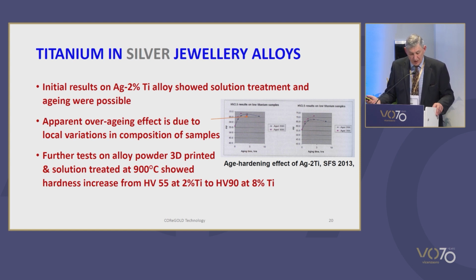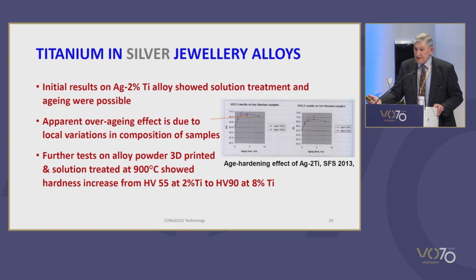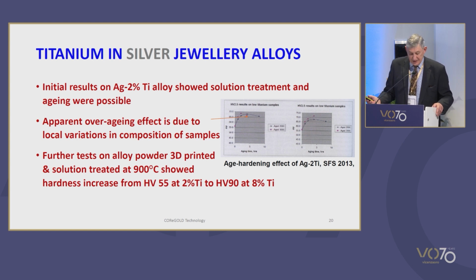The figure gives some results on samples solutionized for 2 hours at 800, quenched and aged. Wright cautioned that the apparent overaging effect is possibly due to local variations in composition in the samples. Further tests on samples made by 3D printing from alloy powder and solution treated at 900 shows a steady increase in hardness with titanium content in the range of 2 to 8%, with a hardness varying from 55 Vickers at 2% titanium to greater than 90 Vickers at 8% titanium in the solution-treated condition.